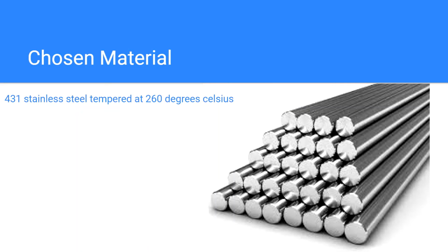A potentially better material choice would have been 431 stainless steel due to its better resistance to corrosion while still meeting the requirement of low cost through its high strength to cost ratio. There were numerous plain carbon and low alloy steels that also met the requirements, including 1045, that would result in a cheaper bolt if corrosion wasn't a concern. Over years of exposure, corrosion in the threads between a nut and bolt can make it impossible to remove. This may be acceptable for some applications where a structure is permanent. However, the goal of the project was to choose a better material, and 431 stainless met all of the requirements and offers a significant improvement in corrosion resistance for only a slight increase in material cost.